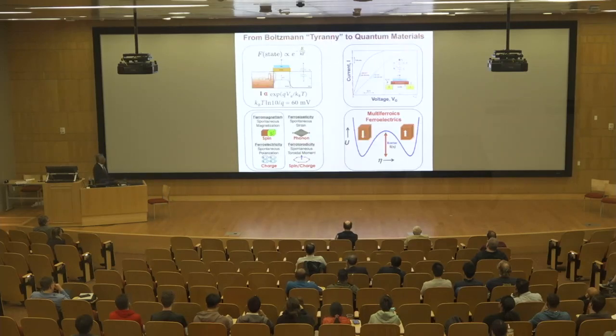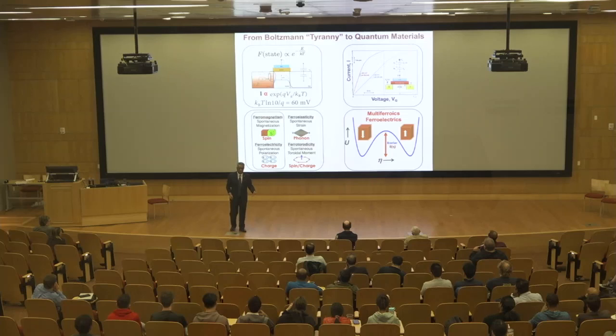One can then capture it in device form. That's a schematic of a standard CMOS device. And this kT log 10 divided by the charge is 60 millivolts. That's called the Boltzmann tyranny, because that comes from the Boltzmann distribution function. For an ideal CMOS device, the slope of this curve is always going to be 60 millivolts per decade. In reality, it's actually larger, typically about 80 or 90 millivolts.